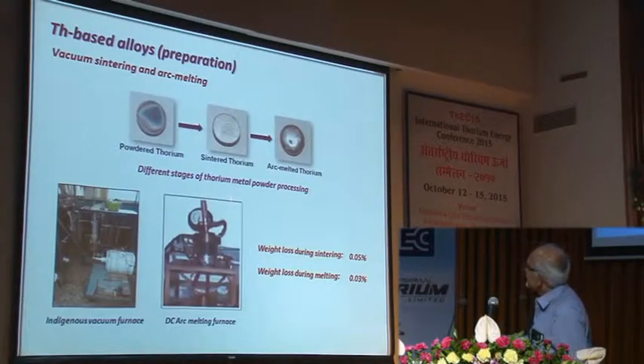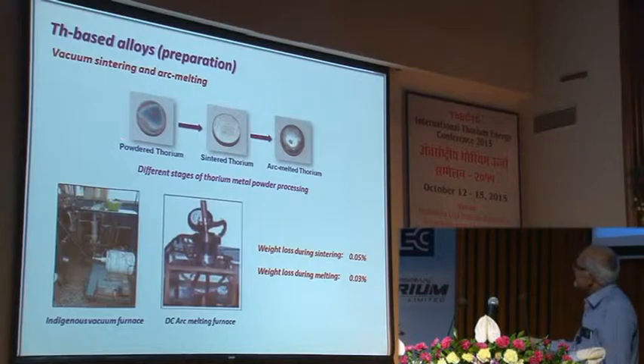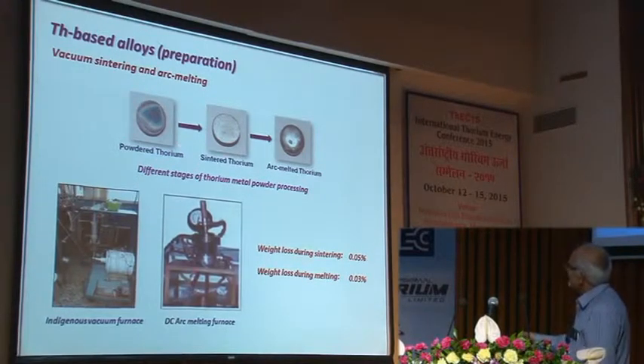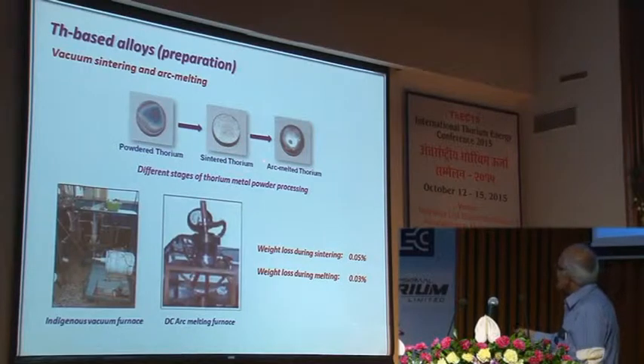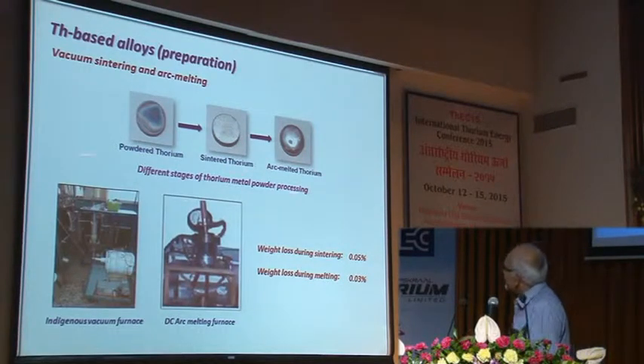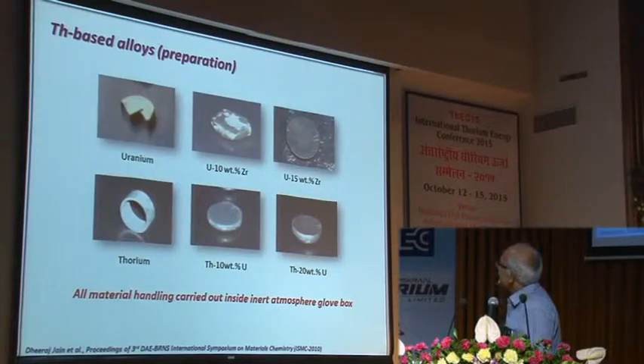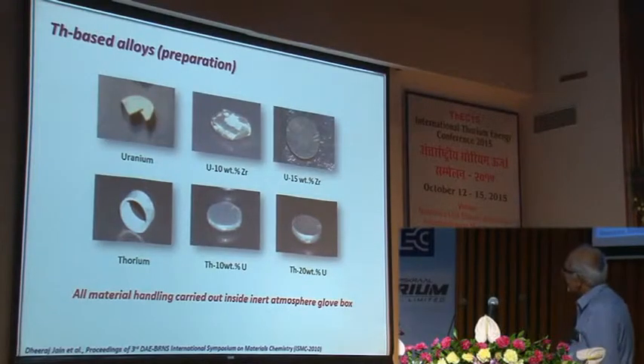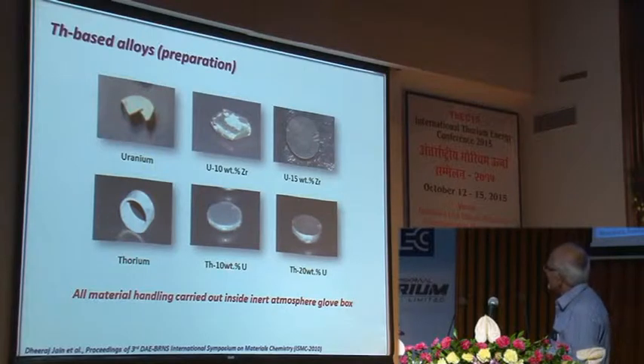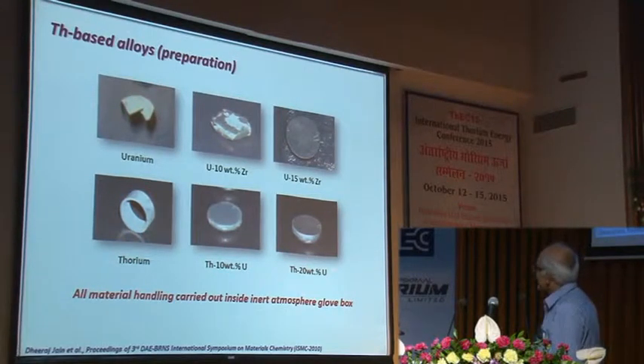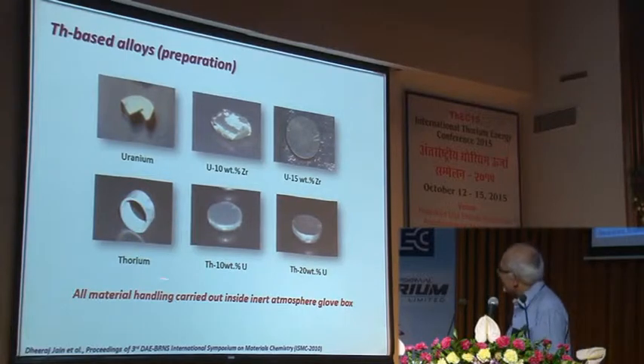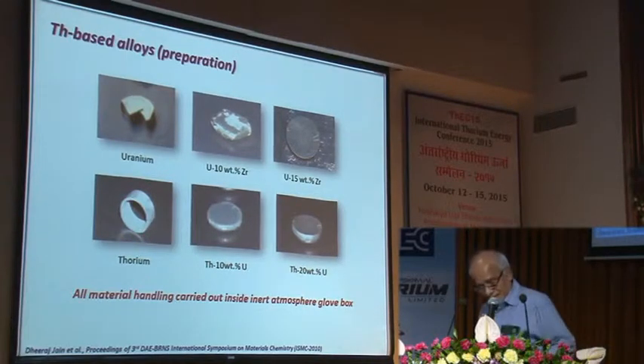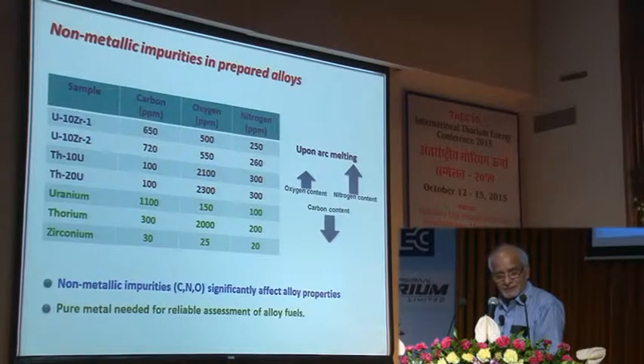Now, the thorium alloy preparation is done through vacuum sintering or arc melting. This is powdered thorium, from there to sintered thorium to the arc melted thorium, and these are the different stages. And finally, we arrive at these alloys, and this is the uranium thorium. This is thorium 10 wt% uranium, thorium 20 wt% uranium, and all this material handling has been carried out inside the inert box atmosphere.